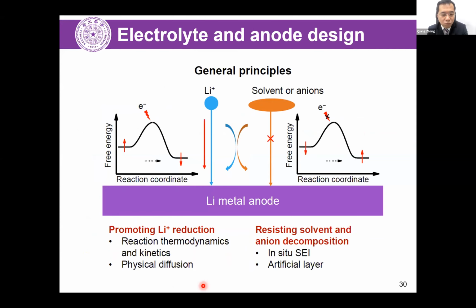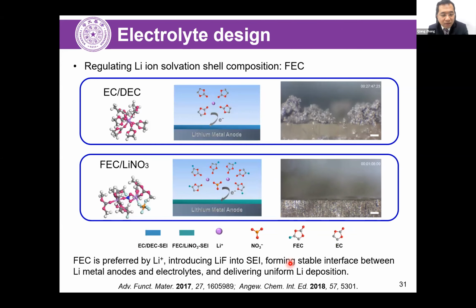So in this case, we try to understand what happens here, and then how to regulate the lithium-ion solvent complex structure. Then we can promote the lithium-ion reduction, and we can try to build a stable SEI to avoid decomposition. For instance, we try to introduce fluoroethylene carbonate, FEC, which is a very widely accepted film formation additive in most batteries. It is found that the FEC molecule prefers to be in the shell structure of lithium ion, and such a structure reaches the lithium metal anodes. Once the lithium metal is exposed, the lithium-ion solvent complex will decompose, while the FEC will provide more lithium fluoride deposition on the surface.